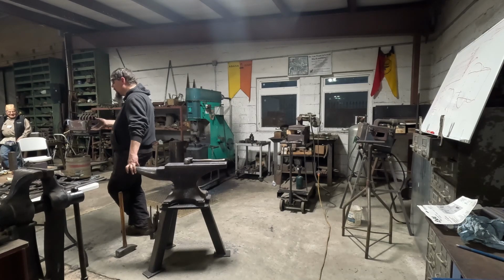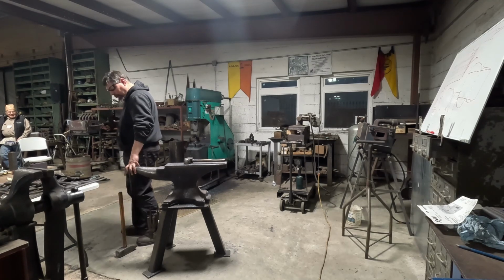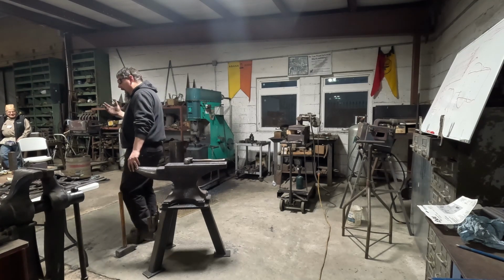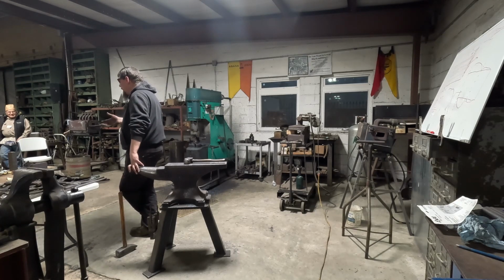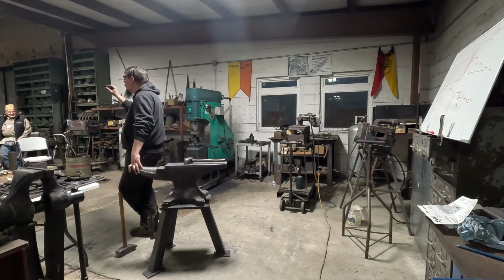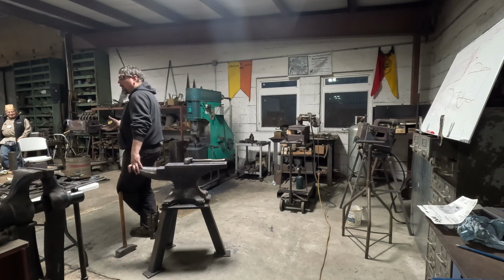But I looked at the type of steel it was, and said, well, this is not typical behavior for this kind of material. It was 4140. So it's not normal behavior for 4140 to behave that way. It's very easy to forge steel. So after the part was cooled, we cut it up, and I looked at it under the microscope, and I found copper streaks in it. And I had no idea where they came from.